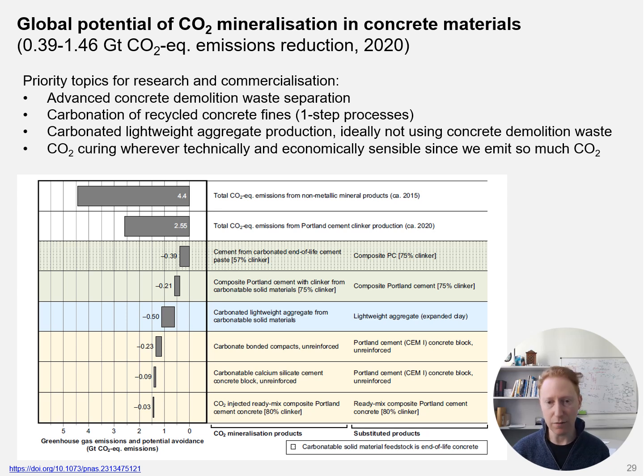The main insight from this analysis is that we should be improving concrete demolition waste separation, we should be improving carbonation of recycled concrete fines, we should be applying carbonated lightweight aggregate production, but ideally by carbonating carbonatable solid materials that are not concrete demolition waste, because that material can be used for the production of carbonated recycled concrete fines. And then we should be applying CO2 curing everywhere else where it is economically and technically desirable.